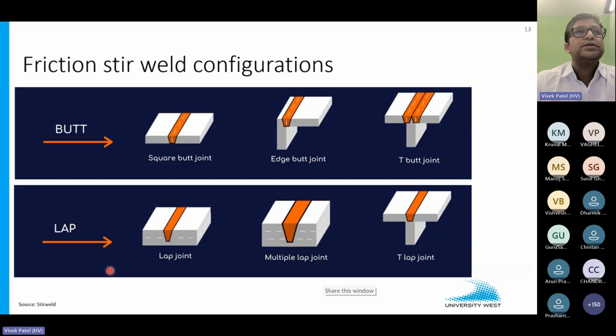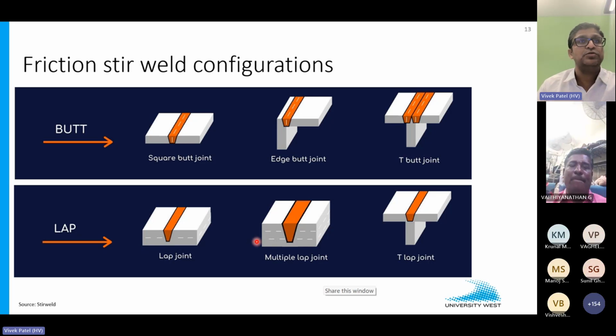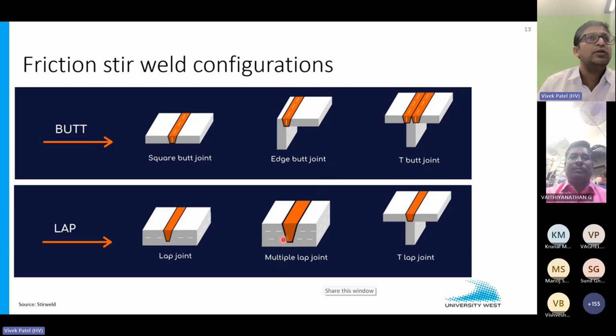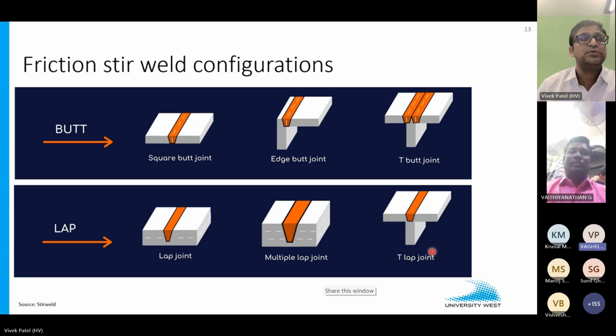Then joint configuration. Friction stir welding allows all different types of butt welds, and also lap joints. And in lap joints, you can have multiple lap joints. That is the beauty of this process. You can have multiple sheets, 1, 2, 3, 4, 5 on top of each other, and you can pass the tool and join all the sheets or plates together in one welding pass, which is quite difficult by the fusion method. And of course, nowadays, because of the fixtures and tooling, T-lap joints are also possible. So it can take care of different weld configurations. That also provides a lot of freedom to the designer for designing the component.